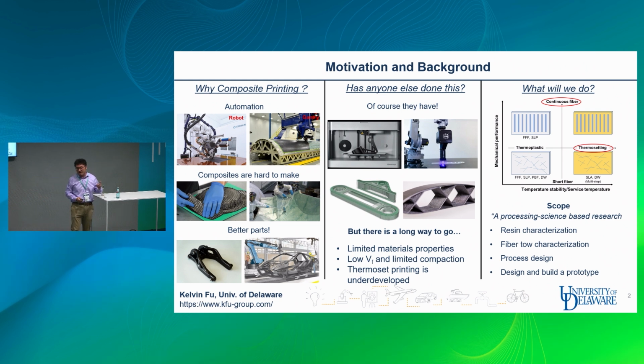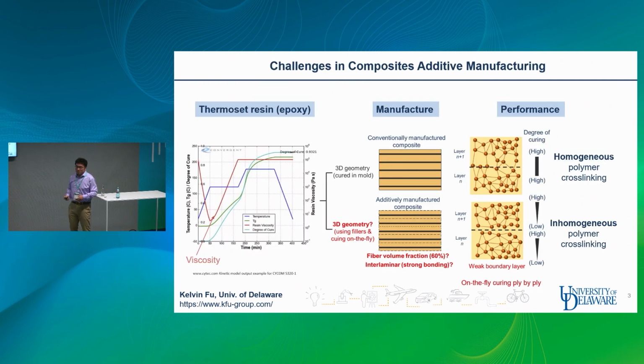We want to understand the challenges and develop a mechanism to solve these problems. Everyone is talking about composites, but why is epoxy 3D printing so challenging? Here I summarize a few challenges. The first one is viscosity. Even though we call it thermoset, it doesn't mean that if you apply heat, the material will cure or solidify. If you look at this viscosity curve, the red line, when you apply heat, the viscosity decreases significantly. That makes it troublesome to cure and retain the geometry during printing.